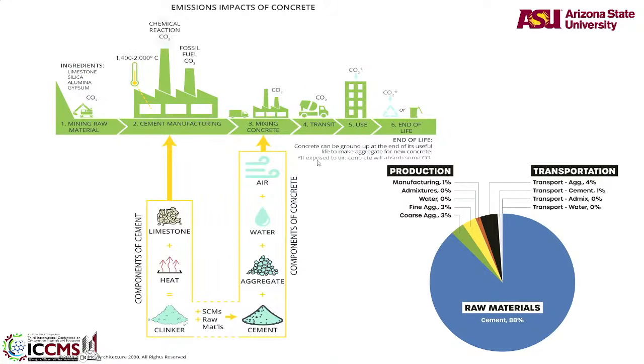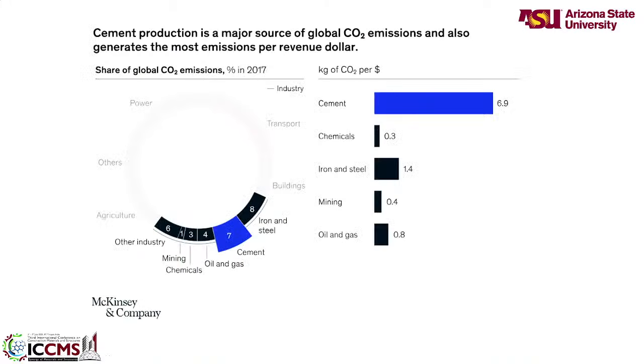But if you look at the emission impacts of concrete as a whole, so cement, of course you do limestone and heat, you get clinker, plus you add SCMs, raw material, cement plus aggregate plus water. Somebody smartly put in air also, just to make sure that you're not complaining about the voids. And then you mix and you get concrete. But at the end of the day, 88% is attributed to cement, 80 to 85% depending on who you talk to. So cement still is the biggest contributor to emissions and energy impact of concrete.